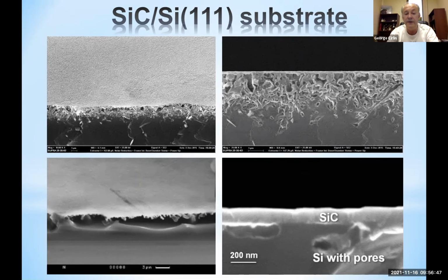What also has to be mentioned here is that due to effective diffusion of silicon into the silicon carbide layer, a significant number of pores appear just beneath this silicon carbide layer, which can be seen here or here. And depending on the growth parameters used, the number and the density of these pores can be different.